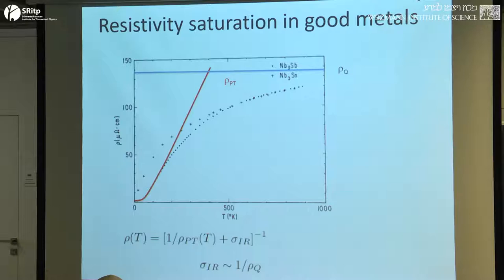Functionally, it fits very nicely to the following expression. Calculate the resistivity, ignoring the fact that you're getting into dangerous territory. Just take the Bloch-Grüneisen expression for the resistivity, which in this range of temperatures, where you're at temperatures above the phonon frequencies, means that the resistivity is simply linear in temperature, so extrapolating that is easy. And then add it in parallel to some other resistance, which has a value that's on the order of the quantum of resistance, and this gives you an expression that moderately well fits this. There are some theoretical attempts to derive this, but there's actually no real theory of this. So this resistivity saturation is an old, unsolved problem.